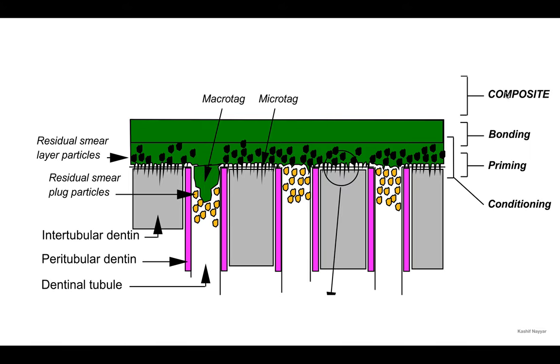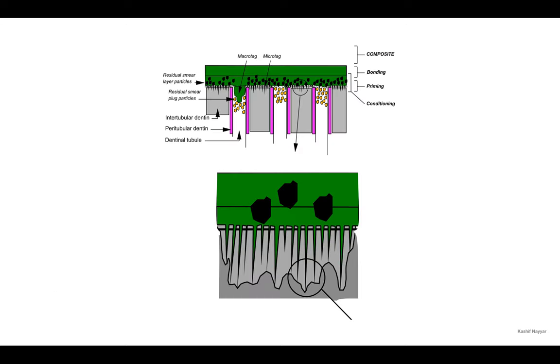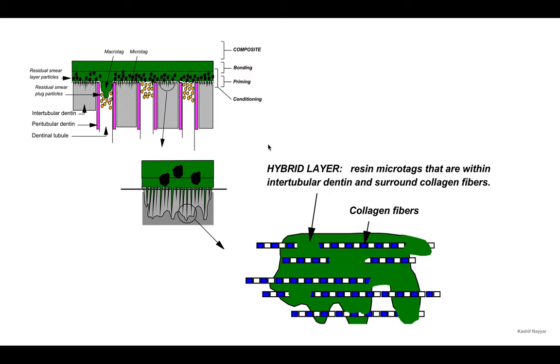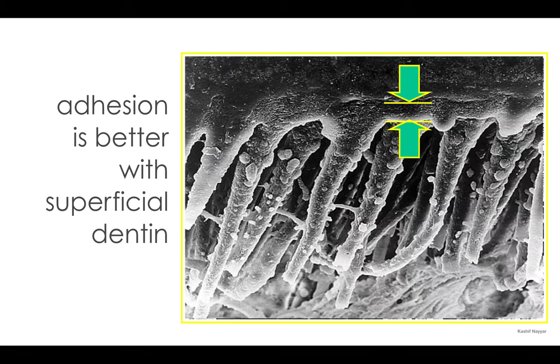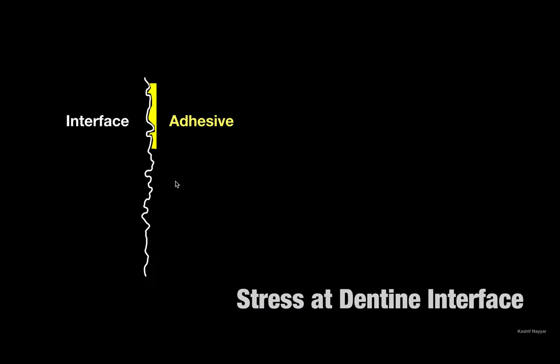So in this illustration we have composite, a bonding and a priming here, and during conditioning this much area was affected during acid etching. So exposing some of the collagen fibers, and the bonding is penetrating inside these irregularities, okay, giving you excellent bonding strength. And at the same time, this hybrid layer, remember when I showed you in the beginning, is basically what? These collagen fibers and the bonding resin, there is a chemical interaction between the collagen fibers and the bonding resin. So adhesion is better with superficial dentin.